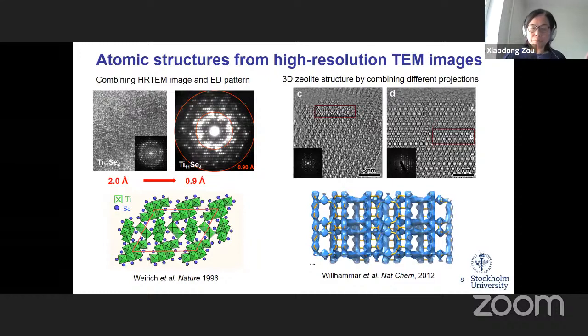And if you have complicated structures, you need to combine images from different orientations. This is an example of a zeolite where we combined images along two different projections. What we do is extract the amplitude and phases from each of these images. In this case, the images contain a lot of disorder, as you see here, so they are not strictly periodic. A very small area, a few nanometers in size, is already enough to get the amplitude and phases. When you combine this information, you can get a beautiful 3D structure model of this zeolite. The images approach, which we used in the early days, is very demanding. To solve such a structure usually requires many months or years, because it's very difficult to collect very good images.